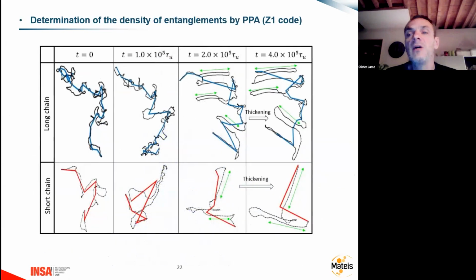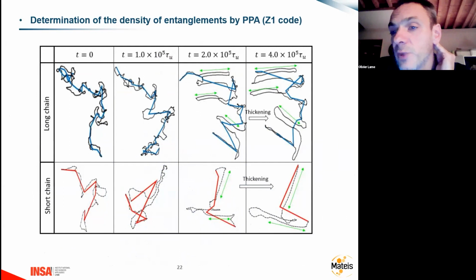Okay, so now I will finish with the determination of one of the most important parameters for the amorphous phase, which is again completely invisible in reality, which is the entanglement, the ability of the chains to entangle together, which prevents the mobility and then plays a significant role in stress transmission and then on the mechanical properties.